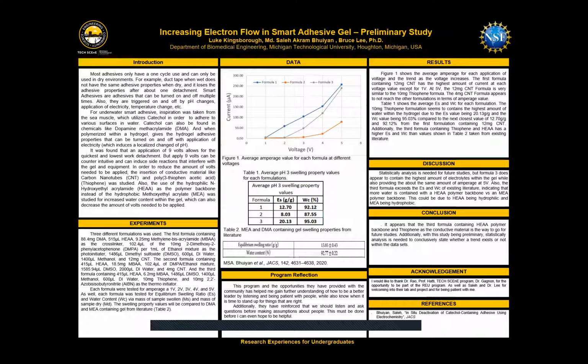So figure 1 shows the average amperage for each application of voltage, and as the voltage increases, the current also increases, but it seems that the first formulation had the highest amount of current for each voltage point, except for 1 volt, where the third formulation, the thiophene formulation, had the highest. And it's unclear whether or not the first formulation containing 12 milligrams of CNT is actually statistically higher than thiophene. Additional statistical analysis is needed to conclude that.